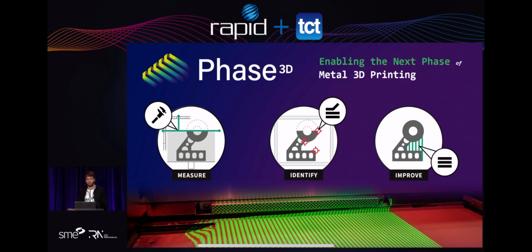But there are algorithms that get way more analytical and quantitative. Essentially, we're encoding a sine wave of light onto the surface. For every pixel on the surface, there's a phase value that corresponds to the phase of the sine wave. Then something gets put on the surface, and the phase of each pixel changes, spatially forward or back in that sine wave. Then through triangulation, based on the spatial phase difference, we calculate the height from a reference. We take a before and after scan, and we know the height difference between the first scan, which is like the datum, and the second scan, which is like the object.